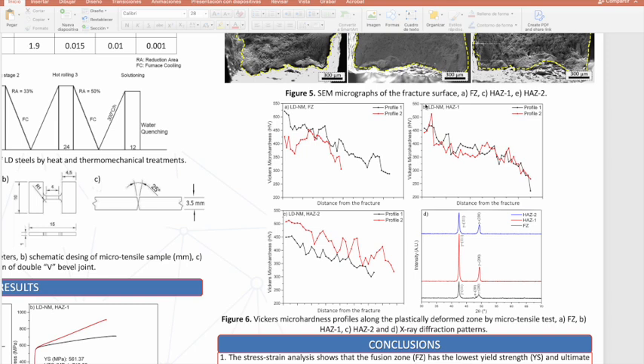Figure 6, subsection D, X-ray diffraction patterns. Figure 6, subsection D presents the diffractograms obtained from the samples deformed by the micro-tensile test. The presence of the austenitic phase is evident, indicating that it remains the predominant phase under various processing conditions, including hot rolling, solutioning, and welding. The diffractogram displays the dominant peaks of iron in the 111 planes and iron in the 200 planes.